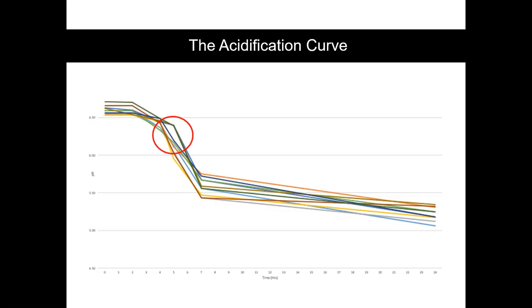We're going to hang on to too much moisture, it's going to be pale in colour, chalky, and crumbly. Gouda is intended to be an elastic style of cheese, and we need the pH to remain almost in the lag phase all the time that we're taking whey off those curds. Most of the moisture that is ever going to come off a Gouda curd will come off before it comes out of the vat, which is the point at which we're pre-pressing. So as long as we're in that flat phase of the pH curve while we're working with the curds in the vat, we're going to be able to make a good Gouda.